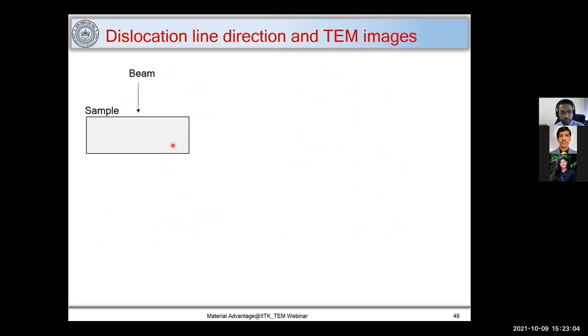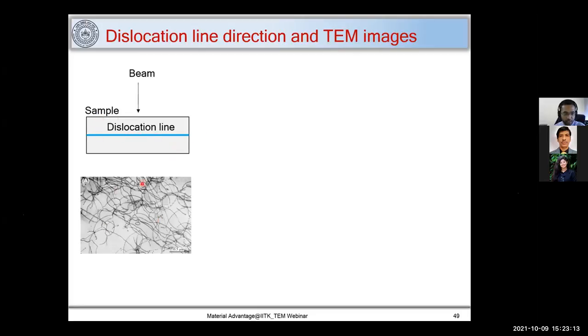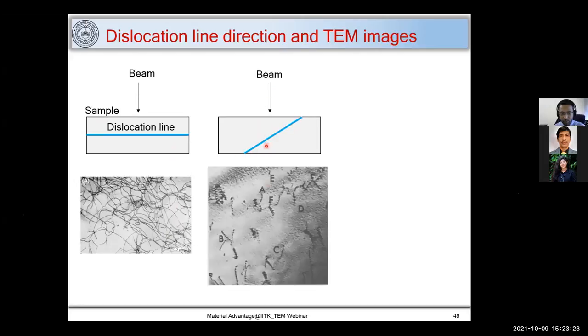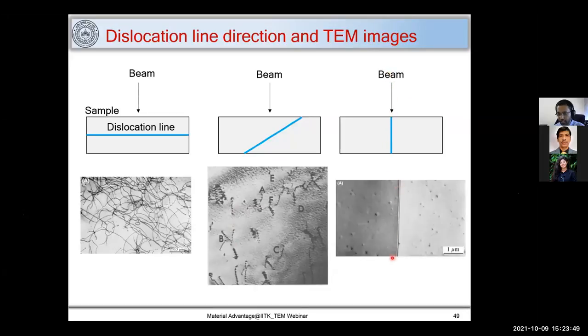Let me tell you how a dislocation line causes contrast. Say you have a beam, you have a sample, and a dislocation line parallel to this sample. You will see dislocations like this in a microstructure. If a beam is falling on your sample and a dislocation line makes some angle with this beam, you see some kind of contrast in the dislocation. You can see bright and dark contrast occurring in these dislocations. Here you have some plain contrast, but here you have bright and dark contrast, from dislocations inclined to the surface. If the dislocation line is parallel to the beam, you will see dislocations like this.